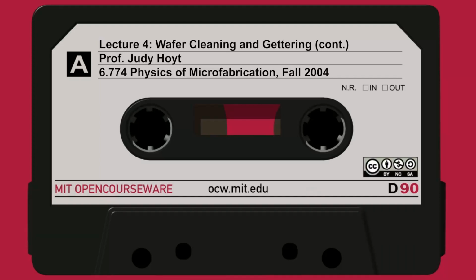At the same time as this happens, the silicon itself will be oxidized by the H2O2, by the peroxide. So we're forming these metallic ions on the wafer that can then dissolve, and at the same time we're growing a very thin layer of silicon dioxide, SiO2. And that silicon dioxide gets stripped in the HF dip of the next step.